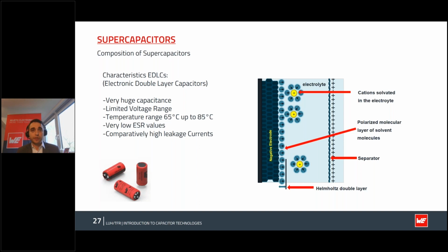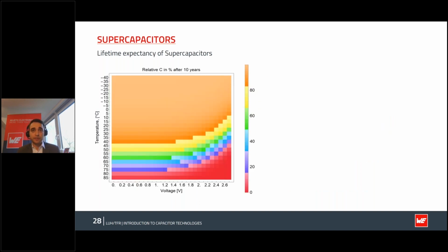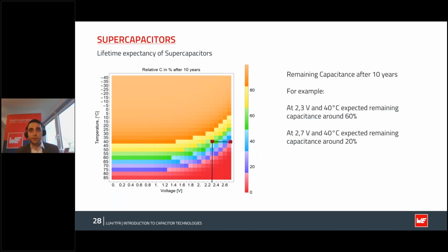On the next slide, I'd like to show you how they age. So here you see the aging over 10 years. And you can see on the left the applied temperature range, and on the bottom the applied voltage level. And on the right, the color coding says how much capacitance you lose. To get a little more specific here, I'd like to pick 2 points. So at 40 degrees, we'll apply 2.3 volts. And you will see after 10 years, you still have around 60% of the capacitance. And if you use 2.7 volts, you have only about 20% left. So this 0.4 volt really has a significant effect when it comes to the aging you see here.